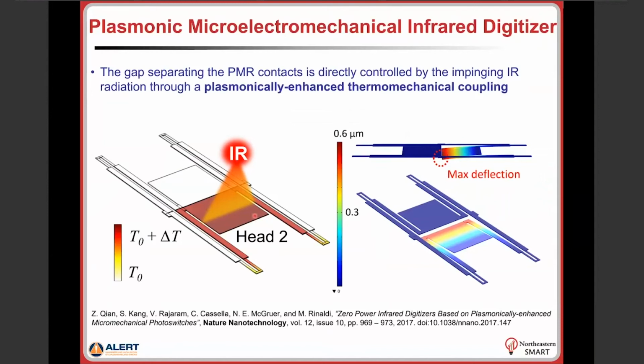When the device is exposed to infrared radiation matching the plasmonic absorber that is defined on the head of the cantilever that carries the contact tip, the radiation is efficiently absorbed, and that causes a large variation in temperature of the structure up to this thermal isolation region. What I'm showing here is a finite element method simulation that shows the temperature distribution when infrared radiation is absorbed in this plasmonic head of the cantilever. You see that the temperature of the inner pair of thermally sensitive legs increases, right? And that translates directly in a downward bending of those cantilevers, and therefore a vertical displacement of the head, and therefore the contact tip, that is on the plasmonic head.